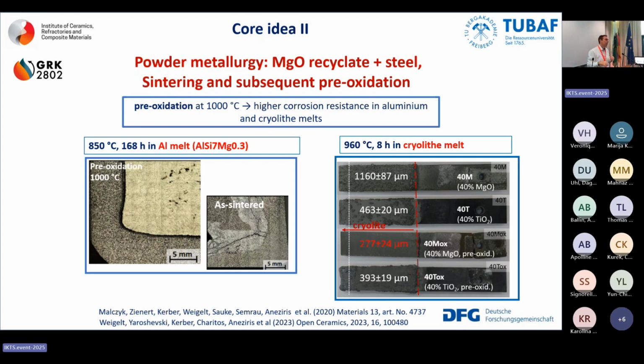You will see it tomorrow. You sinter, and then you have to pre-oxidize. So you create spinels or other solid solutions, as we saw by Inho Jung. And this can protect or decrease the interactions with the aluminum melt. Keep in mind, when you see the presentation of Alexander, in the anodes, especially in the aluminum electrolysis, you create oxygen. So you can also have an in situ oxidation of the metal ceramic component.